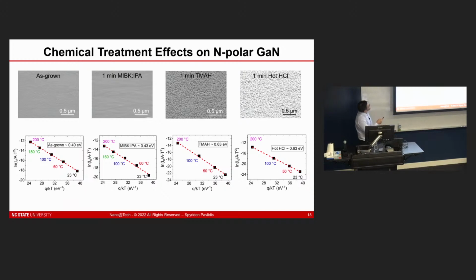And you can see here, these are SEMs side by side of different surfaces after different chemical treatments. That will immediately lead to very rough surfaces, damaging that interface before you put the metal down. What that does is increase your barrier height. And you can even see this coming about if you use something like TMAH, which of course is a common base in developers for litho, right? So we even have to think about how we do our lithography in these kinds of processes. So this is very, very sensitive, right, as far as the material is concerned and the way that the processing is done. So that has impacted a lot of the ways that we've done our processing down the line as well.